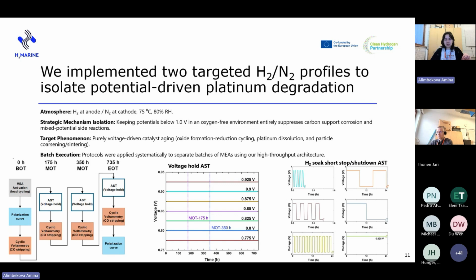And this electrochemical window between 925 millivolts and 775 millivolts gives us the window where we can look at the voltage-driven processes, such as the platinum oxide formation reduction cycles, platinum dissolution, particle coarsening, and so on.